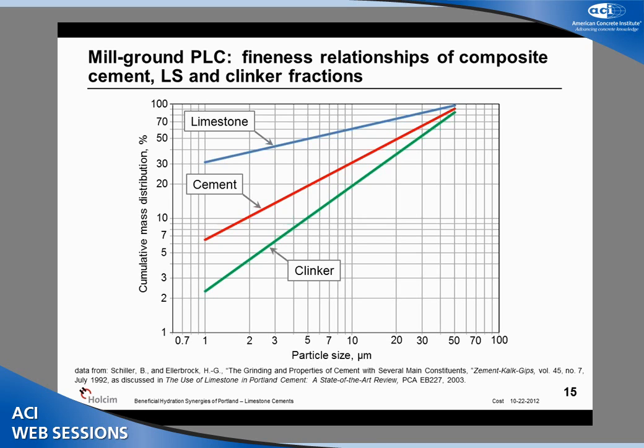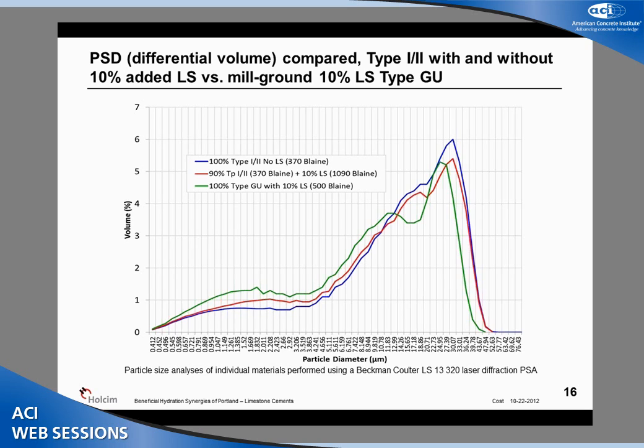When you read the literature on the relative fineness of these materials as they might result from a mill ground system, there's a citation you can read in the handout there on the bottom. This is a graph that appears in one of those references that depicts the cumulative mass distribution of particle sizes for the composite cement in red, the clinker in green, and the limestone in blue. We knew this to be roughly true, but what this is telling us is that as you get into smaller and smaller particles, they become more and more limestone concentrated.